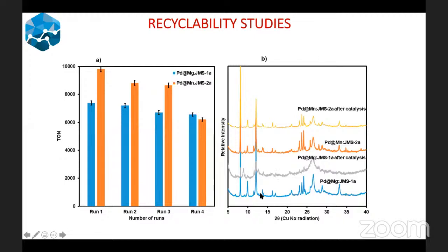We looked at the PXRD patterns of these MOFs before and after catalysis. And we could clearly see that the structural integrity is maintained, but this information is not good enough to explain the observed significant drop in the catalytic activity of our MOFs, especially the Pd@Mn-JMS-2a.